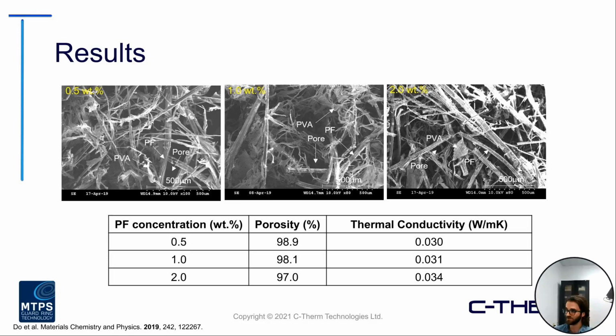And as Adam mentioned earlier, air is a really great insulator. So if you have more material there, more routes for that heat to transfer within the bulk, that will result in a net increase in conductivity. So what they noticed is the lowest PF concentration, the 0.5, was denoted with the lowest effective thermal conductivity measurement, and therefore the most insulative in nature.